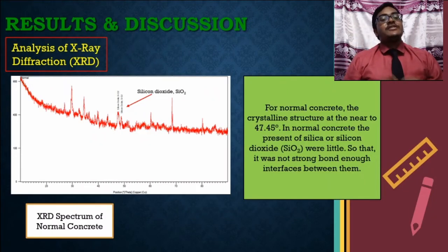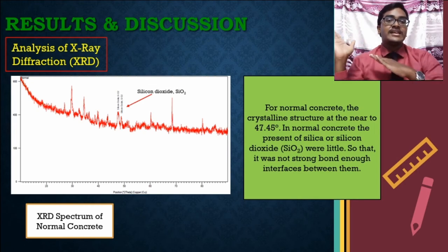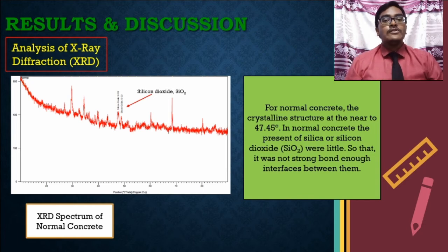Okay, now I'm going to explain the analysis of XRD, which is X-ray diffraction. As you can see, the figure shows the XRD spectrum of normal concrete. For normal concrete, the crystalline structure is near 47.45 degrees. In normal concrete, the presence of silica or silicon dioxide was little, so there was not a strong enough bond at the interface between them.